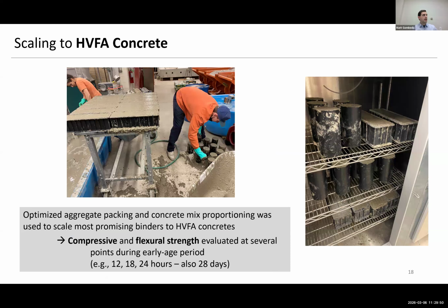So now here's where it was handed over to us at IIT after coming from Penn State. We were then scaling the concrete in larger batches. You can see a lot of flexural strength specimens, modulus of rupture specimens there. In our curing chamber there on the right, you see cylinders as well. And we're focusing on early age properties. So we did 12, 18, 24 hours for the most part. And then we also did 28-day breaks just to be able to compare to the standard time frame for compressive strength testing as well.